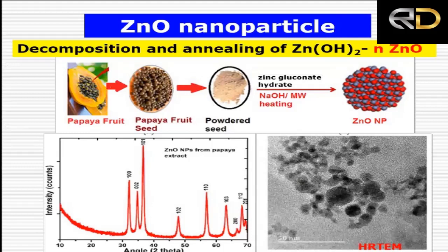Now, another very important nanomaterial is zinc oxide nanomaterial. Zinc oxide nanomaterial can easily be prepared by heating zinc hydroxide at about 400 degrees centigrade, where nano-sized zinc oxide is formed. But normally, we today prepare nano zinc oxide by green route.